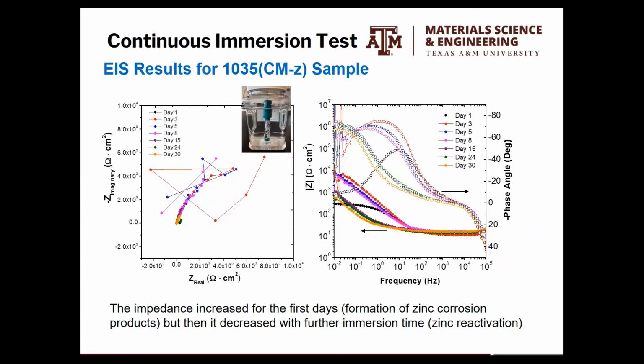Because you see differences, and I can elaborate more at the end, how this Nyquist on the left and the Bode on the right and the phase angle will give you information on the degradation process. That's what we care about in terms of these results, the degradation and the information that we can extract, which I'm going to elaborate on a little bit later.